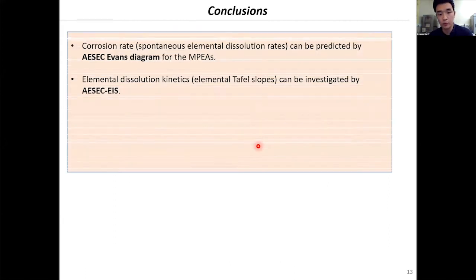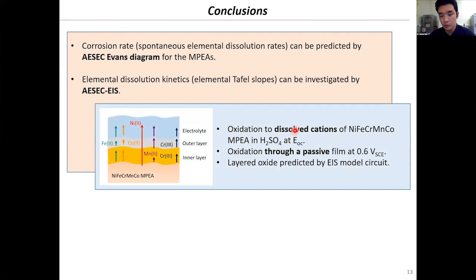So to conclude, with this coupling it was possible to obtain the corrosion rate, the spontaneous elemental dissolution rates, estimated by the AESEC Evans diagram for these complicated alloys. And we could also obtain the elemental dissolution kinetics using the elementally resolved Tafel slope by this coupling. And as I showed you two examples of potentials, at one potential we saw nice oscillation, which means the elements were dissolving directly, forming cations, whereas when we increased the potential to the passive domain, the elemental dissolution occurred through the passive film. That's why we couldn't see the oscillation of elements during the impedance.